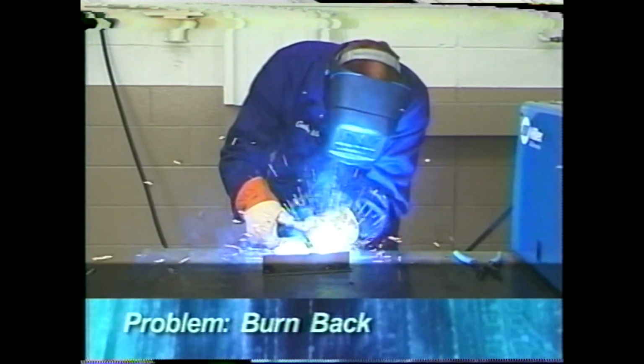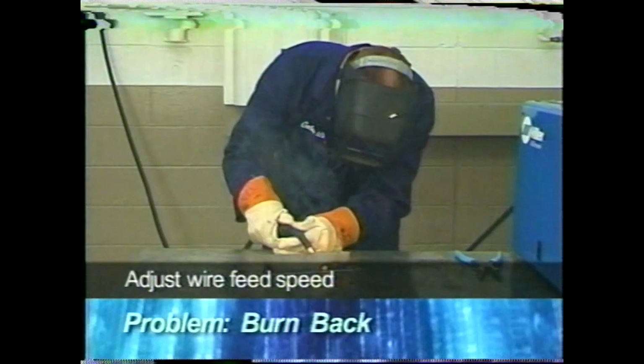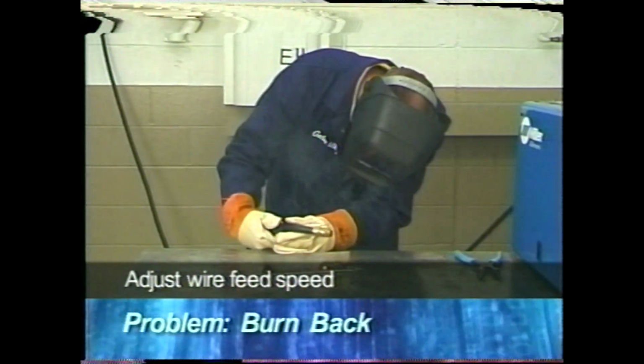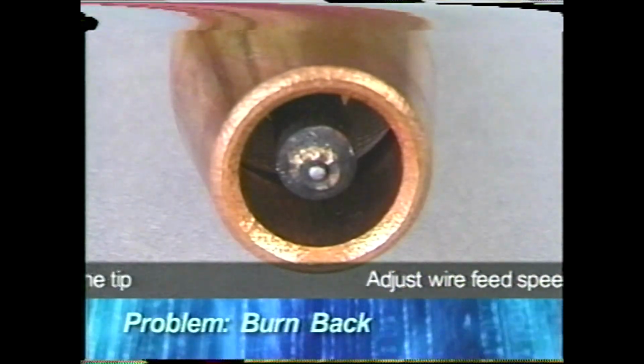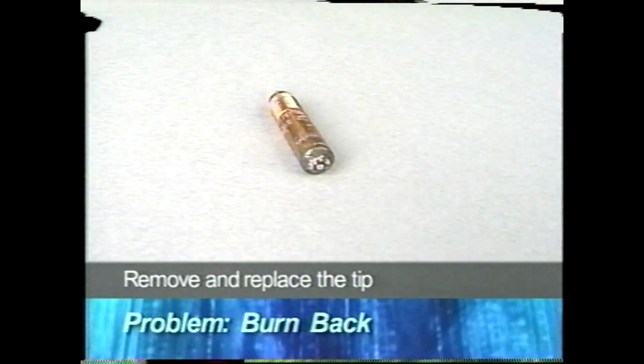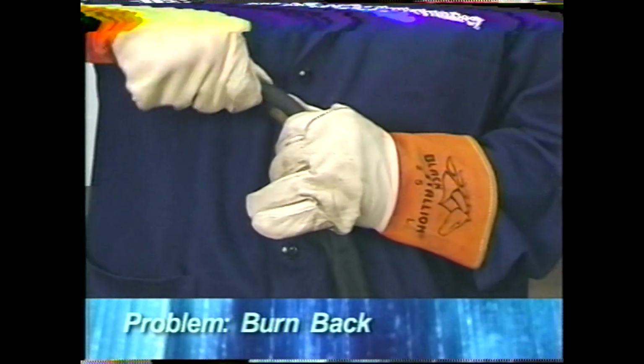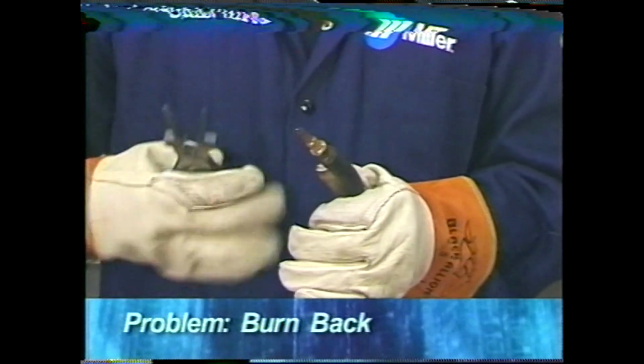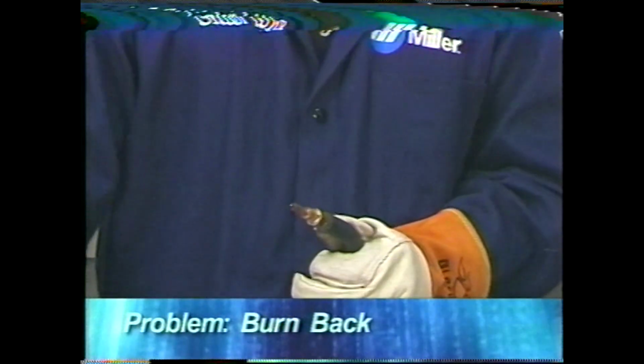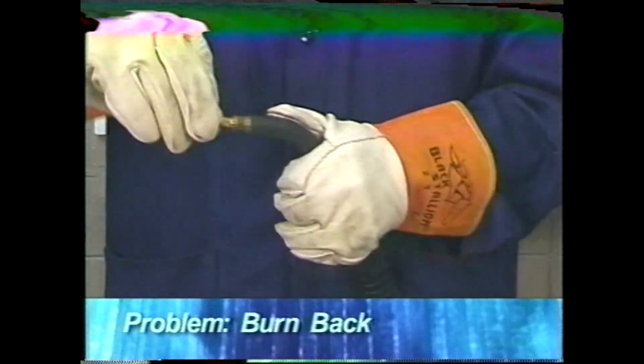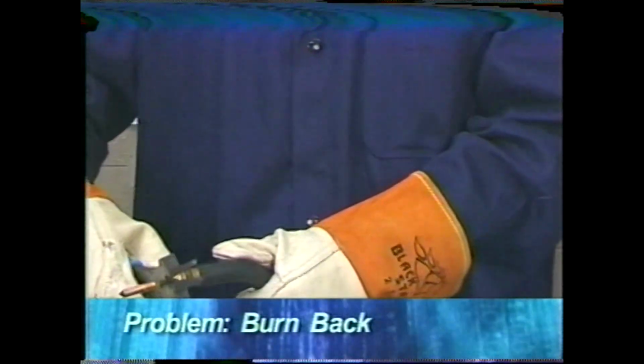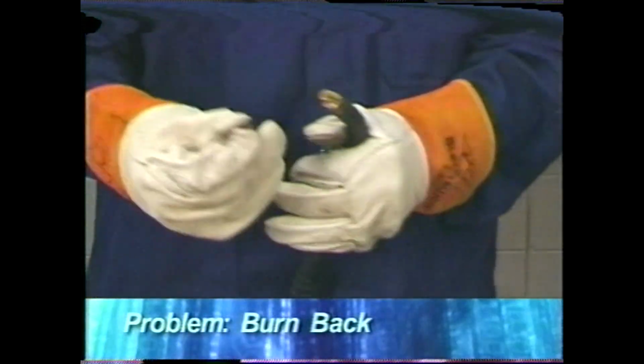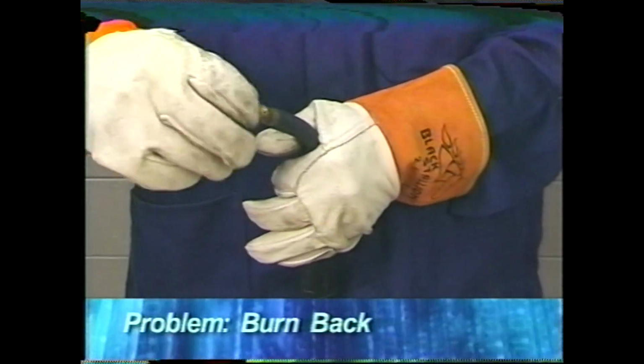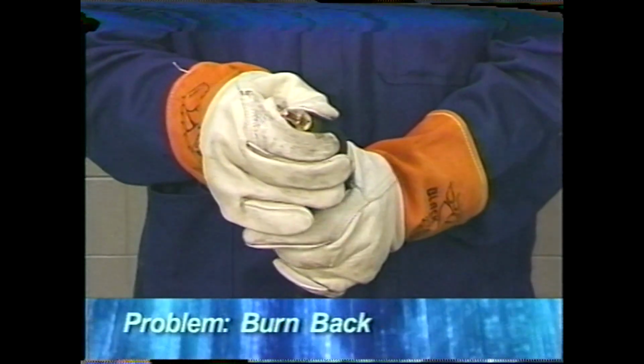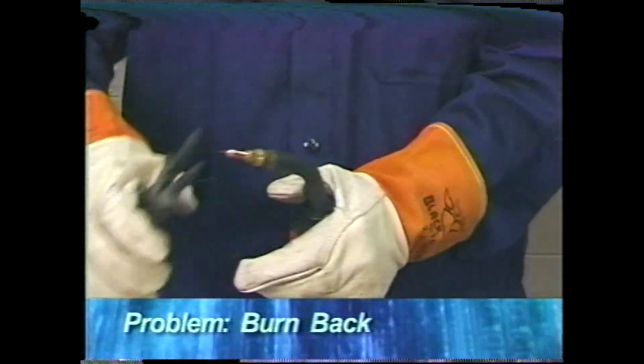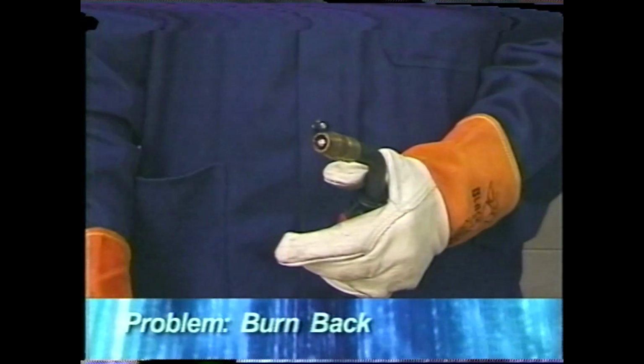Burnback can occur if the wire feed speed is set too slow or if the gun is held too close to the work, and will cause a weld to form in the contact tip. If this occurs, you will need to change the tip. Remove the nozzle, unscrew the tip, which may be melted to the wire, snip the wire off, replace the tip and tighten, and replace the nozzle so that it's flush with the end of the contact tip.